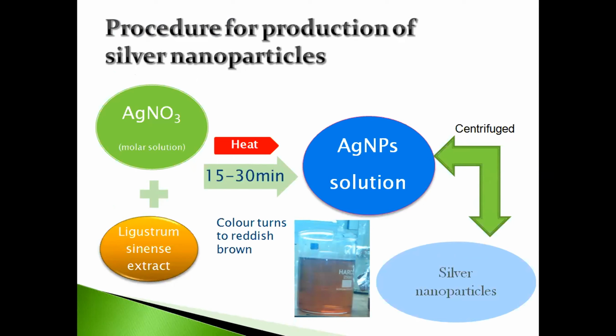And in a separate beaker, you take the extract of the plant, the Ligustrum sinensis leaves extract. I took it by beating the leaves, and after beating them, heating it for 10 to 15 minutes, then taking that extract, filtering it with Whatman filter paper, and then adding that extract to the silver nitrate solution. After adding those two separate solutions into one beaker, we heat that solution for 20-25 minutes, probably 30 minutes, until the color of the solution turns reddish brown.